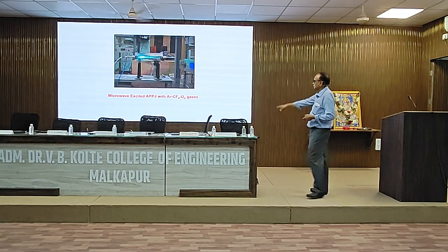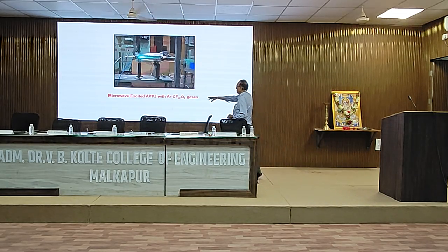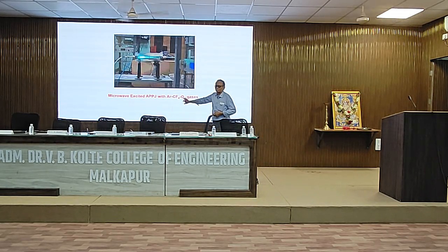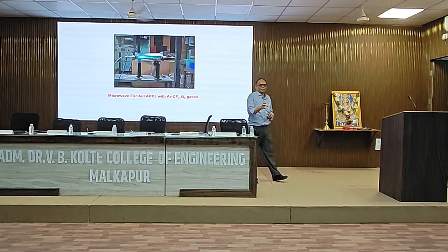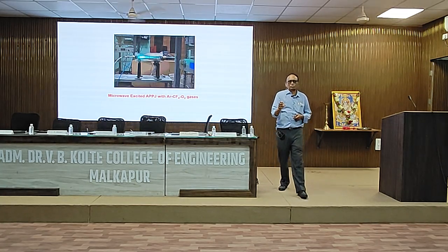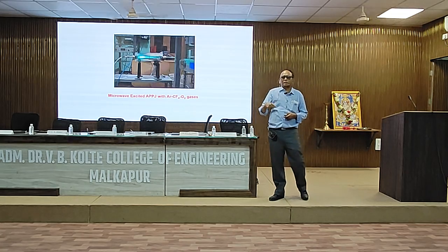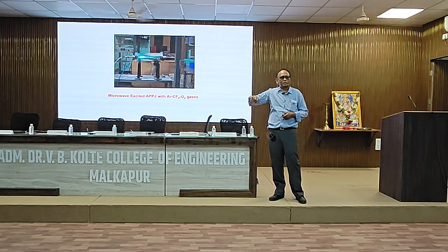And that chemical reaction was using argon, carbon tetrafluoride, oxygen plasma. It generates oxyfluoride radicals, which are highly active. It attacks silicon. It removes that as silicon tetrafluoride, which is vapor.